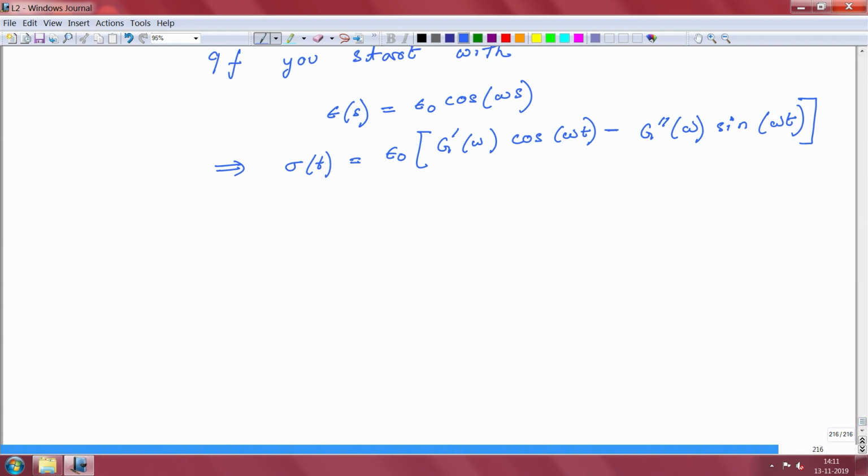Okay. So, now, a couple of points: once again we took some simplifications while deriving this. One, obviously in the very beginning, was that epsilon naught is small, so that we can assume linearity. The second was that the function g t can be broken up into two parts, one is a constant part, another was a time varying part.